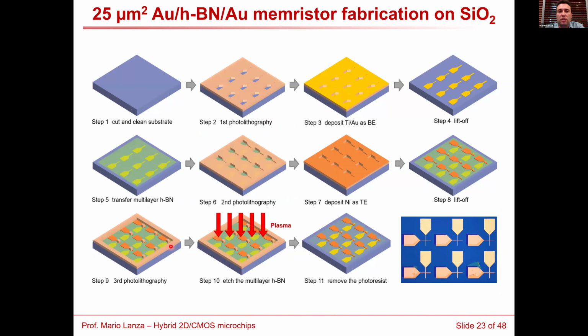And we do the fabrication like this. We fabricate 25 micrometer square gold, boron nitride, gold devices on silicon oxide. You can see the sample. We make the first lithography to pattern the bottom electrode, transfer the boron nitride, another lithography to make the top electrode, and another lithography to open a hole on the bottom electrode so that we have a good electrical contact.